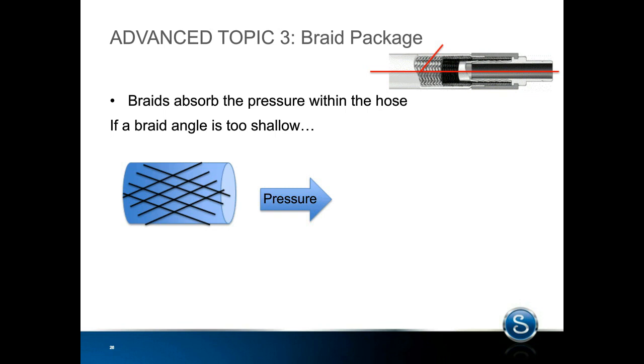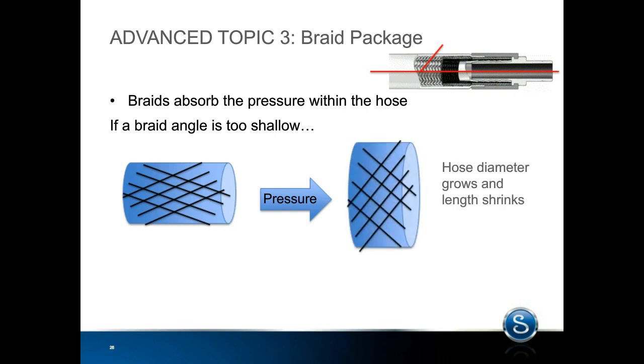So the braid angle is the angle, of course, that the braids wrap around the outside of the core tube, as you see with the red lines. And if the braid angle is too shallow, so these wrap around the hose, I guess, too quickly, what happens is, under pressure, they steepen, and the hose core tube is allowed to grow in diameter.